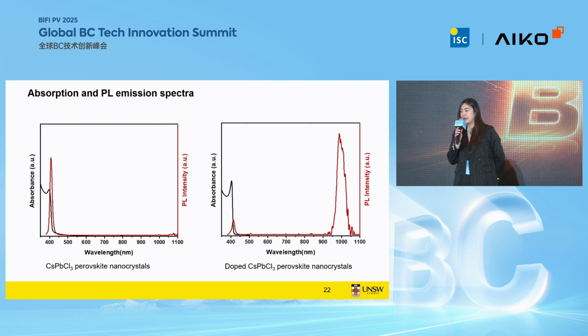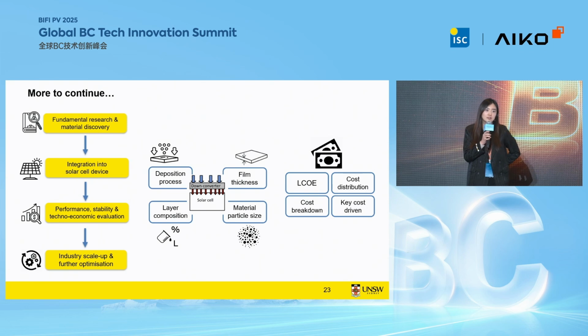Without doping, as I showed you before, it shows this excellent optical performance, with a very sharp emission peak in the visible. But with a certain dopant, it actually has a very strong emission peak in the near infrared, where silicon can also absorb very efficiently. So it's like you are converting one high energy UV photon into two lower energy infrared photons at 980 nanometers. We're successfully seeing this nice near infrared emission, and we are measuring PLQY of more than 100%. And we are on the pathway to further improve it towards 200%.